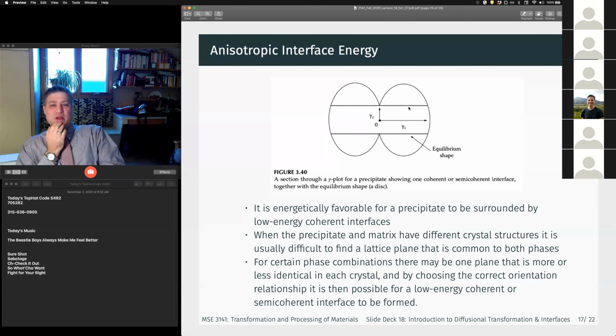So imagine now we have this weird looking double hump plot. This is the interfacial energy as a function of direction. So if I look at the interfacial energy for this plane normal, it's much lower than if I went off at an angle. This distance here is much less than in this direction. So when we have an anisotropy, we can minimize our overall energy by creating precipitates of different shapes. In this case, we're going to make a plate-like morphology rather than a sphere, because if we make a plate, we maximize the amount of this low energy interface that we have.